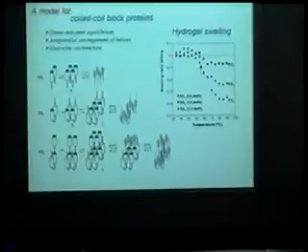And really interesting here is that we think that these, rather than forming a linear structure, actually fold up within each other to form these more compact structures. Also, very interestingly, they display this hierarchy structure, whereas this trimer can be viewed as a combination of a dimer, which is shown here, plus a monomer sitting on top of it.